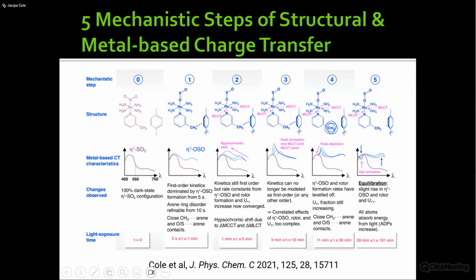So trying to put that all together, we try to make a mechanism that relates the structure and the optical absorption properties. Really just taking those empirical findings, and so obviously this is our dark state, and this is our sulfur bound. This is what the single crystal optical absorption characteristic looks like, and then we apply light, and initially it's first order kinetics dominated by the oxygen bound photoisomerism, with the arene ring rotating just like you've seen in the previous slides.